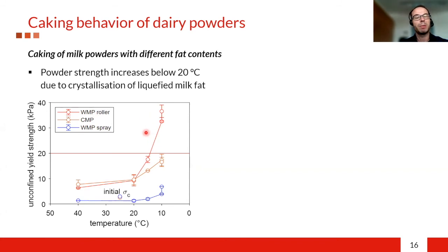This was probably due to the crystallization of the liquefied milk fat, which is mostly at the outer part of the particle. The lower the temperature, the more fat will crystallize and solidify the liquid fat bridges, which formed at higher temperatures.